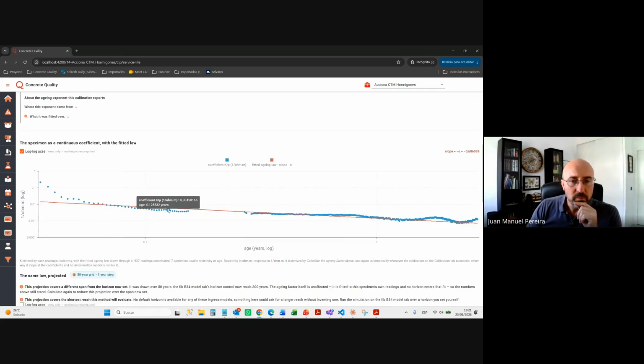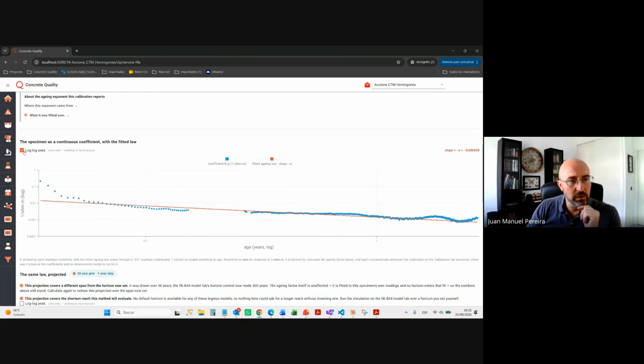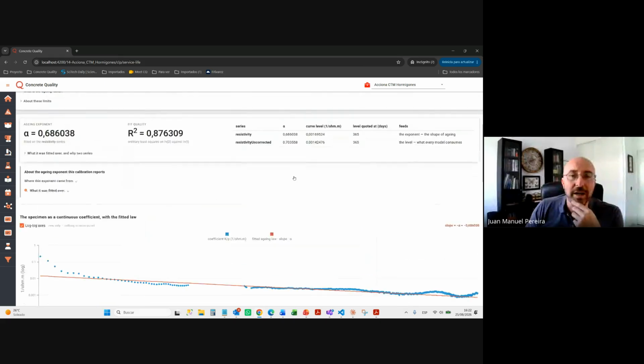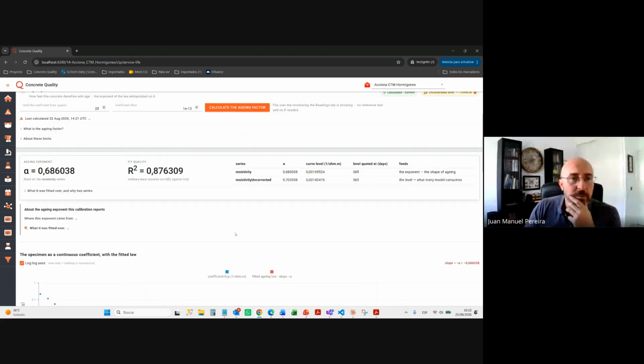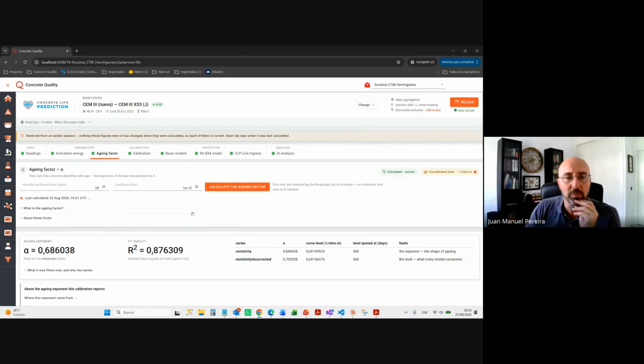You see that there is a very good fit, and we're showing it here on a logarithmic axis. These blue points are the readings, corrected for temperature as we did in the previous step, and this is the aging law. The slope of this curve is that aging coefficient. It tells you how much the concrete will improve over time. When we have the readings, we use the readings. When we don't have the readings yet, because we are predicting for 100 years, we use this, and it is fitted to the real concrete in the real structure, not something tabulated. So it gives you a much better and more precise prediction. This is a key point in doing this monitoring.